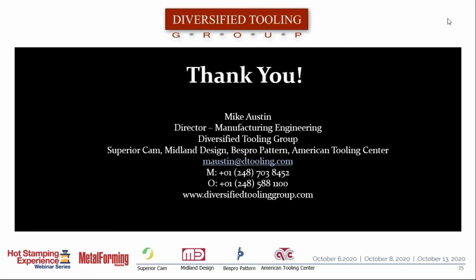The biggest factor, however, tends to be buildup of aluminum silicon coating on the tooling, not cleaning it properly. That causes separation and reduced contact pressure. We like to be at least 5 megapascal of contact pressure, ideally 10 megapascal of contact pressure. And once you start building up any accumulation of material, then you start reducing the contact pressure in other areas of the tool, and those areas start getting hot. That's why you put thermal monitoring on the parts coming out that can help you identify a part that's starting to come out hotter and hotter. That means you've got some coating pickup in there that needs to be cleaned out.